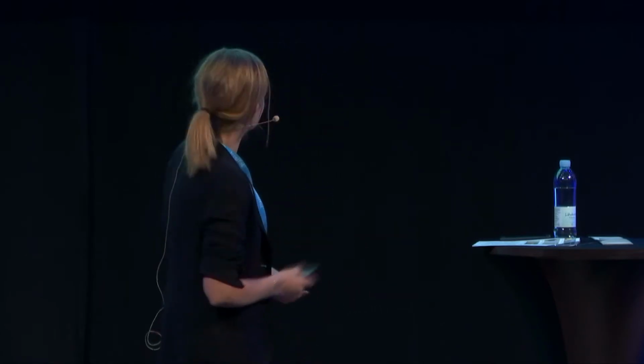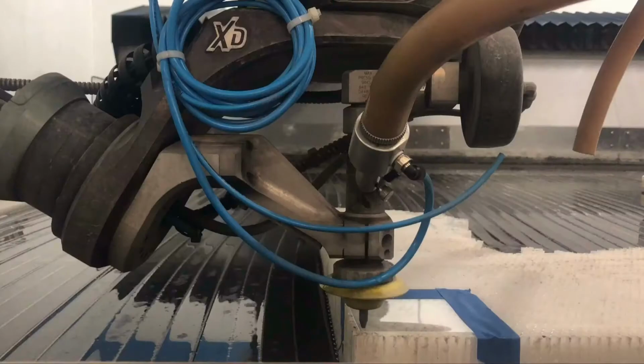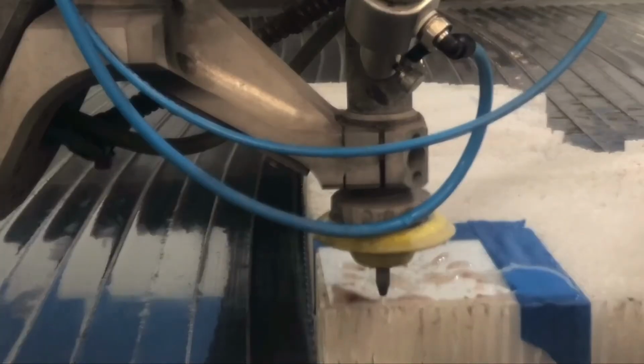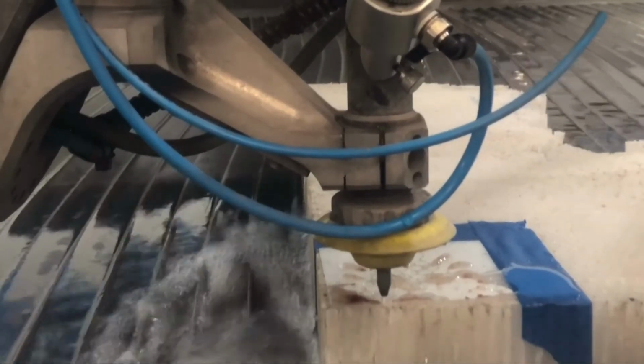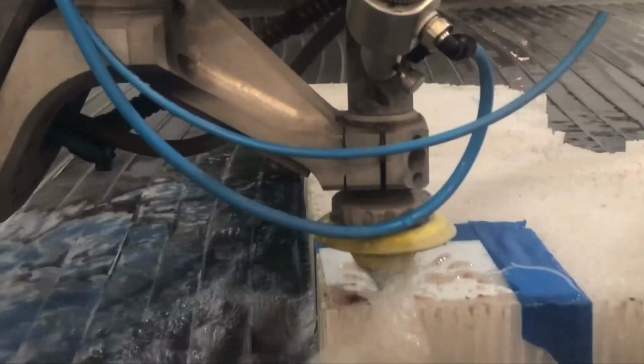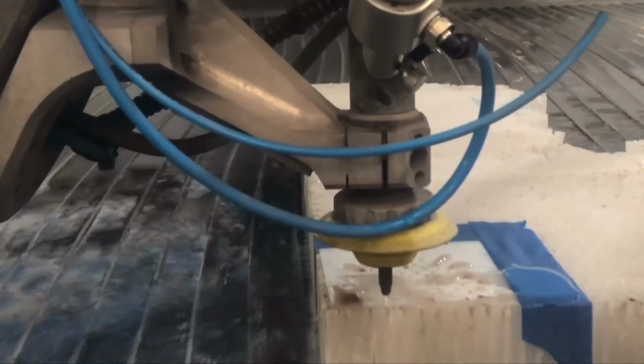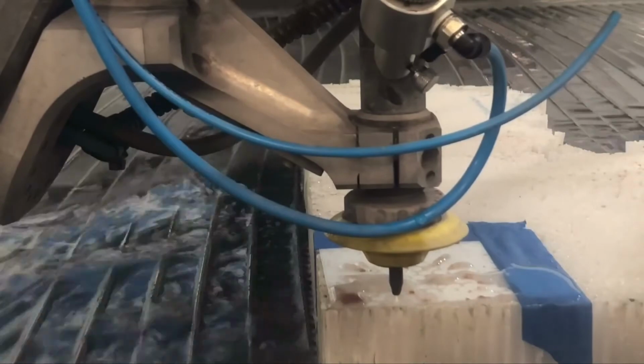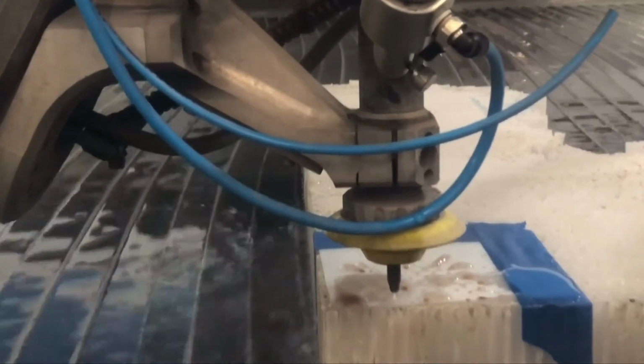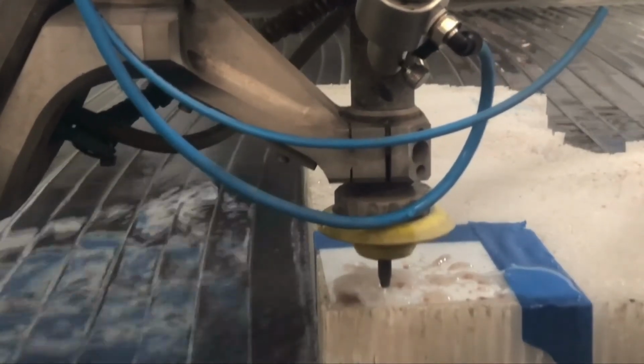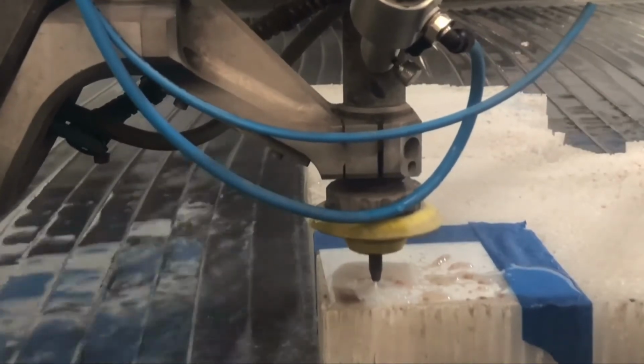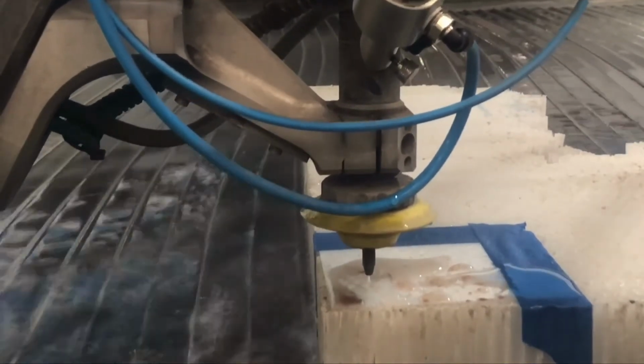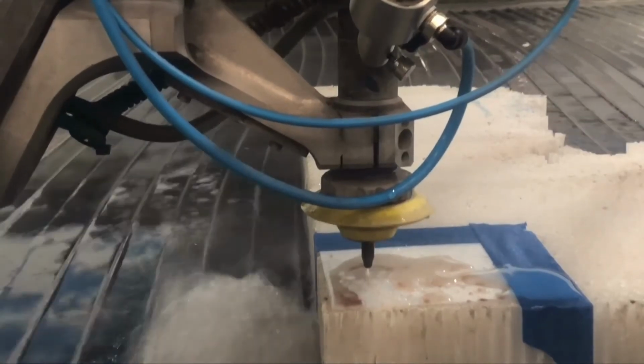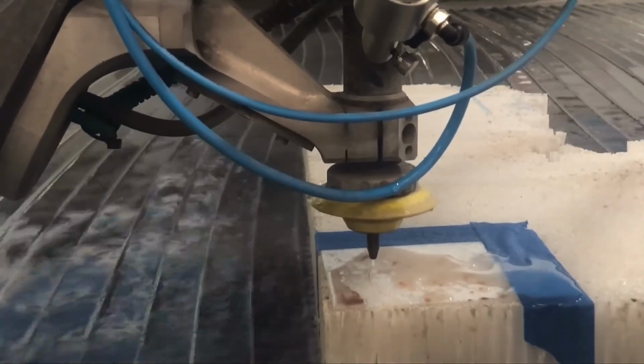it was quite satisfactory. And because we had a water jet available, we also did a couple of stupid things. But this is the nature of exploration, when there's not so much data available, when you're exploring prototyping solutions. So what we did is we used that water jet that's available at the Boston Build Space. It comes with water and this Australian red sand aggregate that's used for cutting thicker pieces of glass. It was just a bad idea.